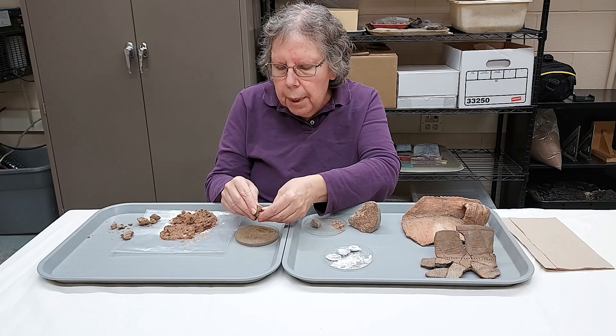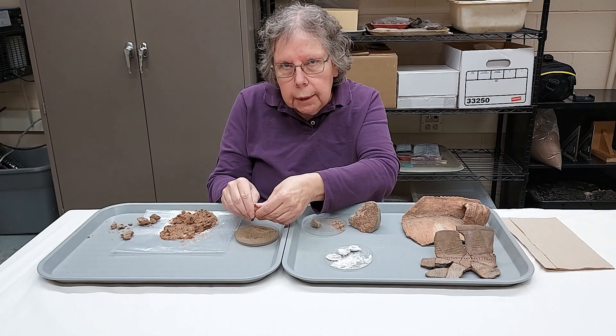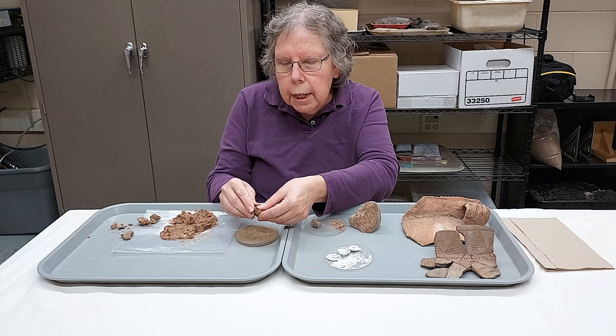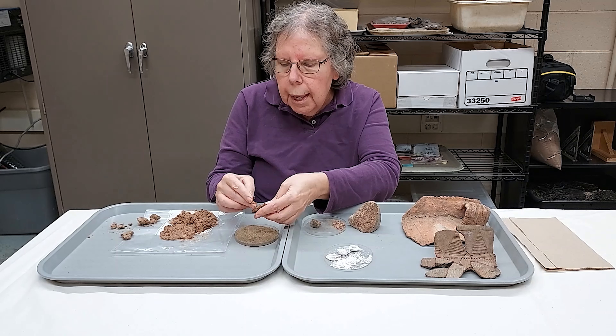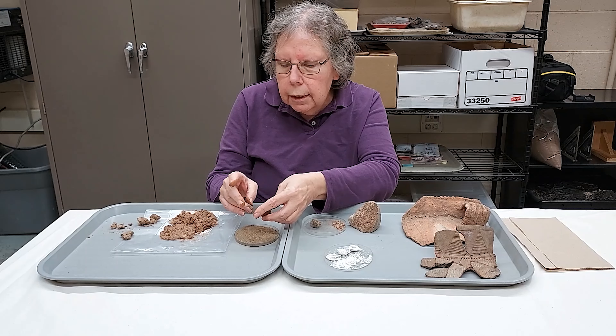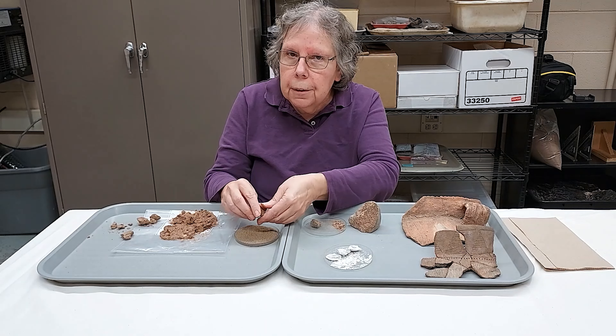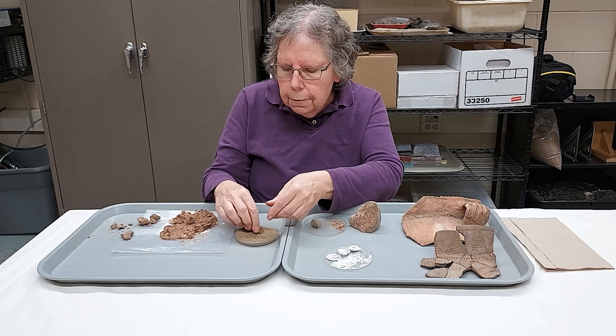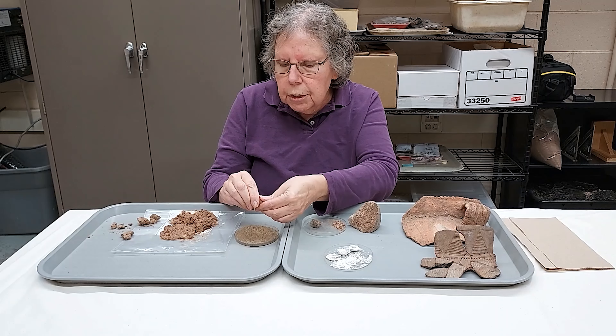When people were making this pottery they were forming it by hand. There was no wheel in Native America in North America, and they were open-air firing it — in an open air fire rather than in a kiln — and the temperature would get up potentially to 1,500 degrees Fahrenheit. These are pretty hot fires, and they would have made very good cooking pots and water storage vessels.